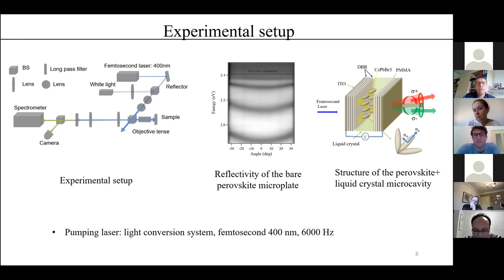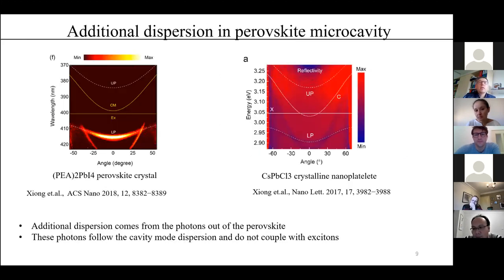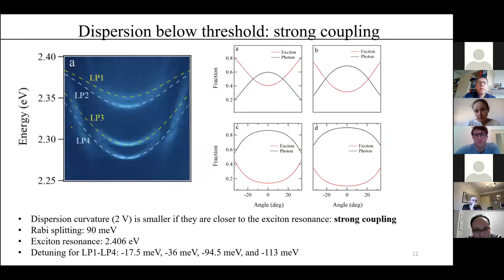So then on slide 11, there is this double layer of this mode, which, as I said, at room temperature, one has to be careful about this strong coupling, I believe, because this is the problem with this refractive index. So maybe this is this horizontal-vertical splitting of the modes, just because of the anisotropy of liquid crystal that it introduces to the cavity. So that was my long question.